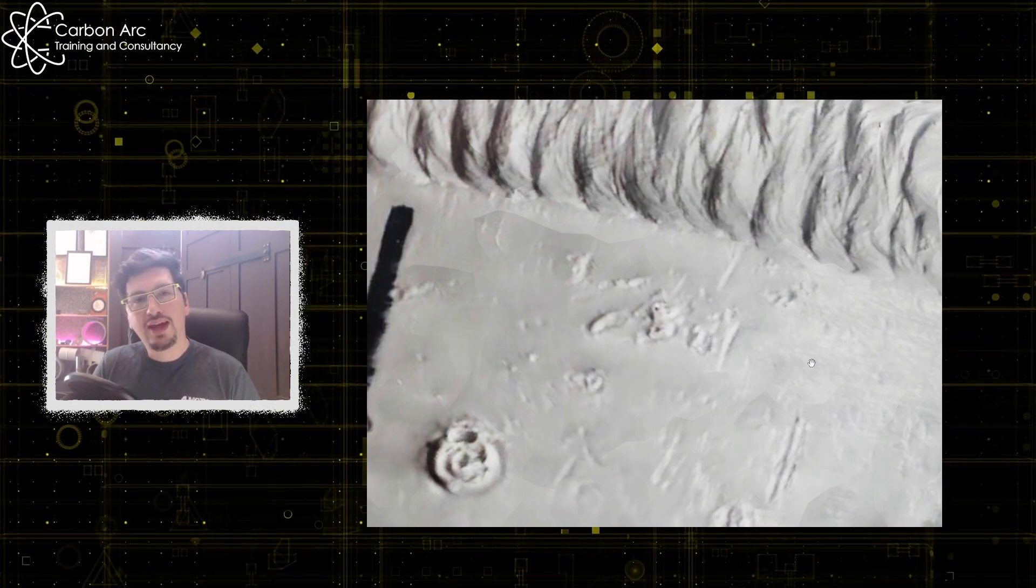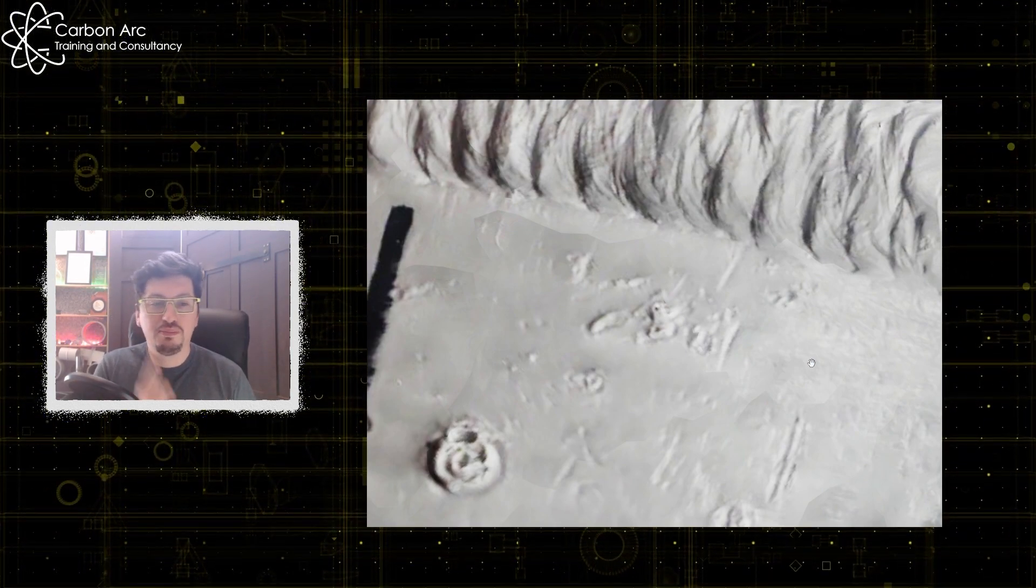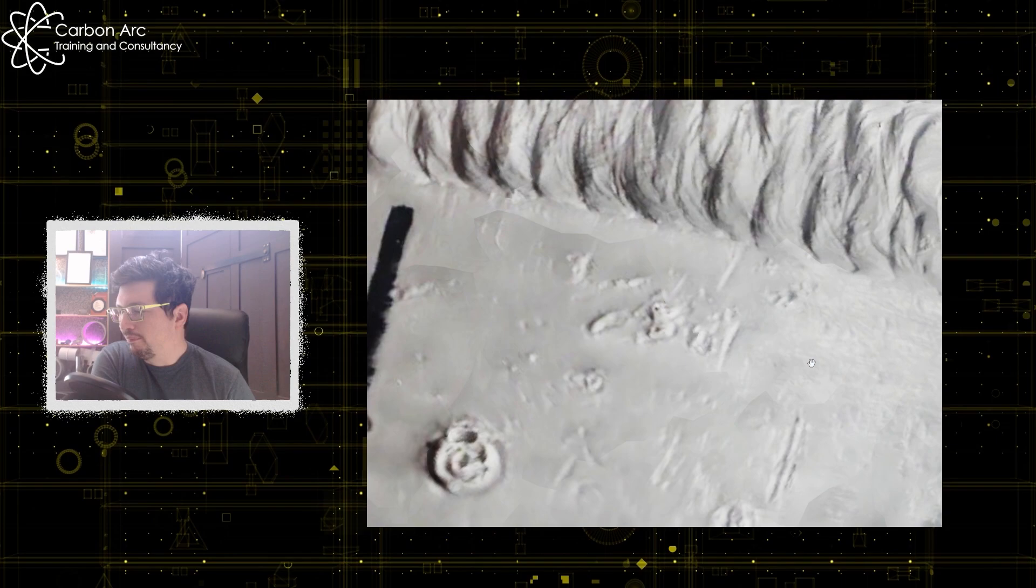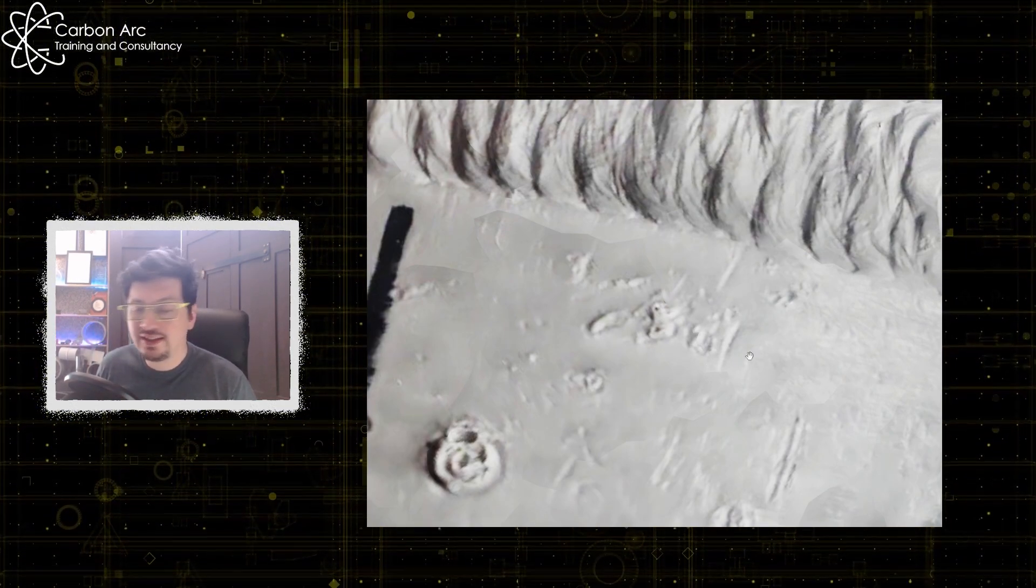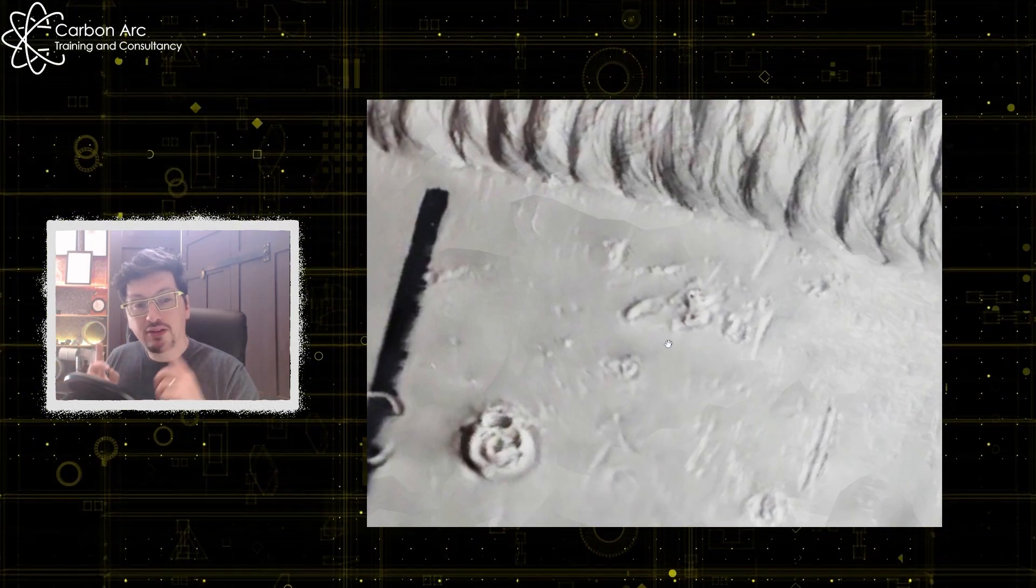So in most engineering standards, you're not allowed any. Some allow one. But most of the time what we'll be doing is taking this defect, grinding the surface off to remove the hardened area and then carrying on.